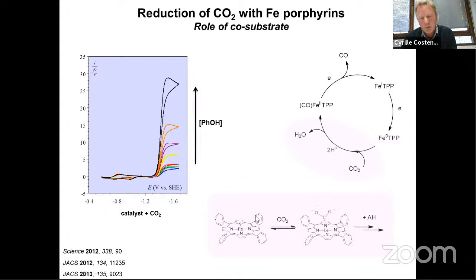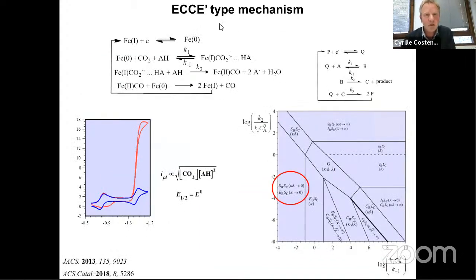So you can propose a mechanism where you first have addition of CO2 on the electro-generated iron 0 porphyrin, and then in the presence of water or phenol you put on the oxygen to break the CO bond. So actually, this is the mechanism that you can propose, where you generate iron 0, then you add CO2. A first molecule of acid will stabilize the charge on the CO2, because actually you have a transfer of charge from the iron to the CO2 in this inner sphere process.